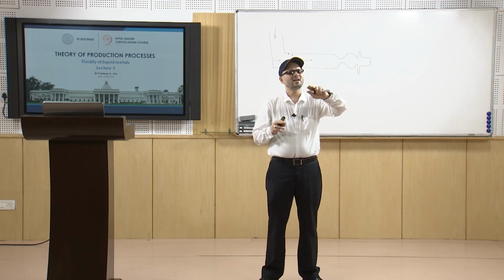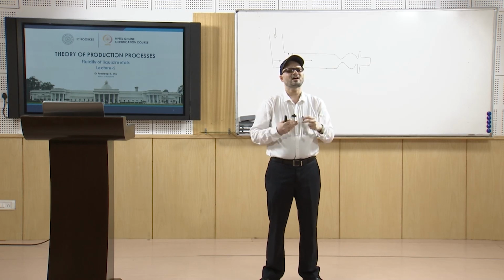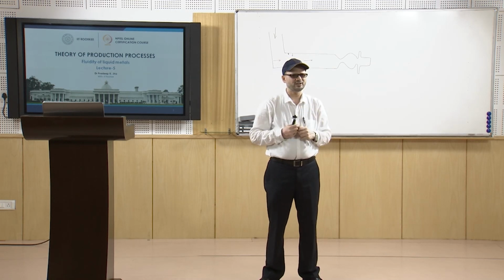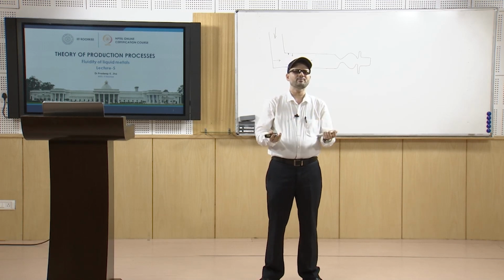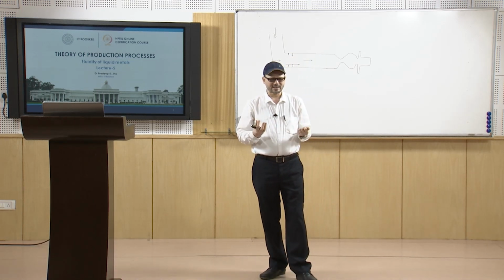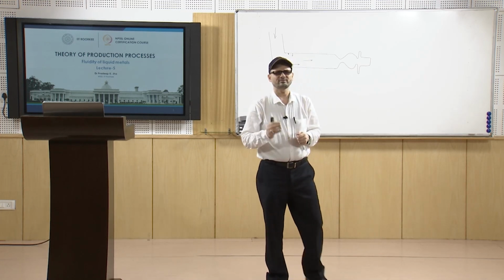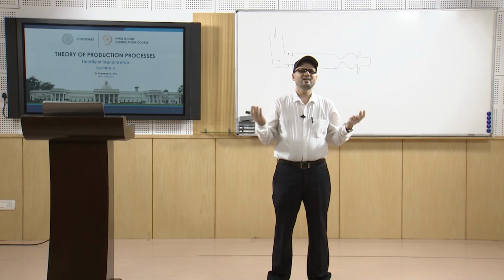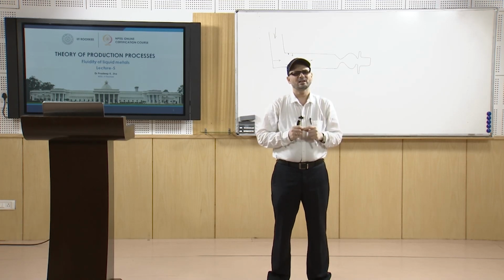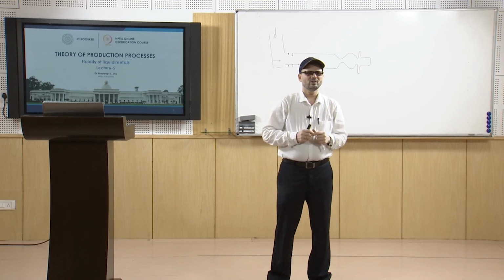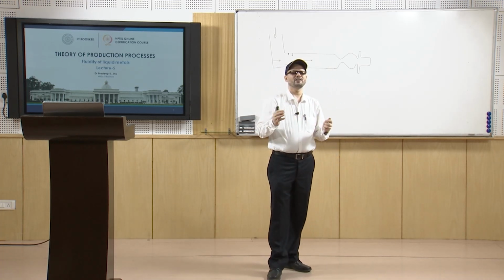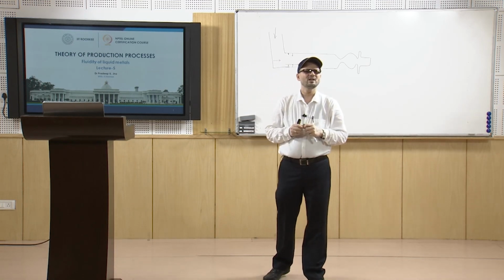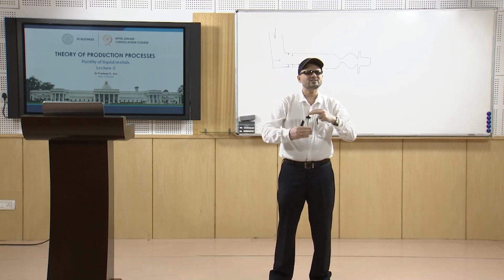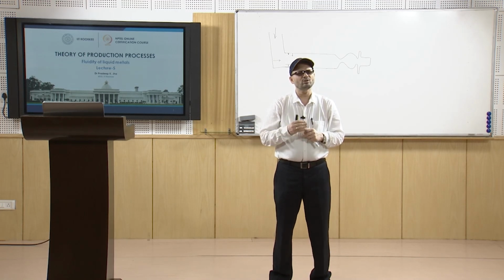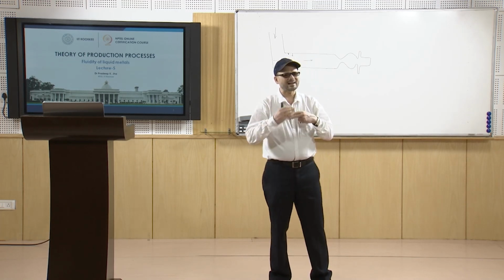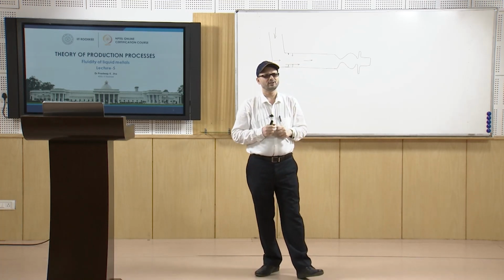Any metal which you are casting will have certain surface tension properties, it will have the property whether it makes oxide films, and what is the gas content of the liquid metal, because at higher temperature large amounts of gases are dissolved into the liquid metal. That will affect the fluidity. Similarly, you have inclusions which are suspended in the liquid metal, and how it is getting solidified, the mode of solidification. These are the factors which affect the fluidity.